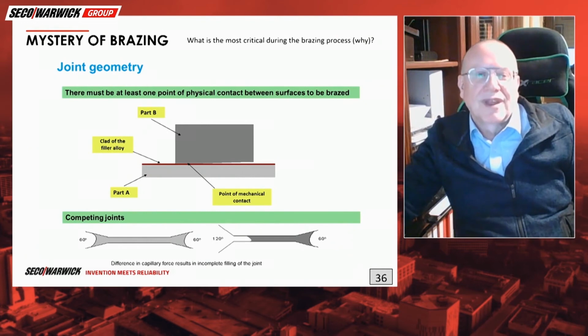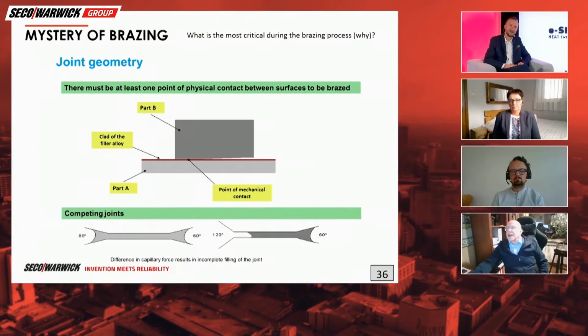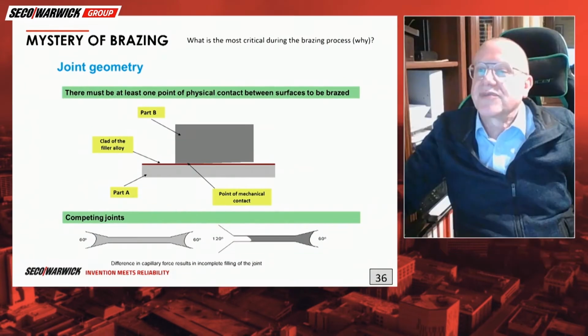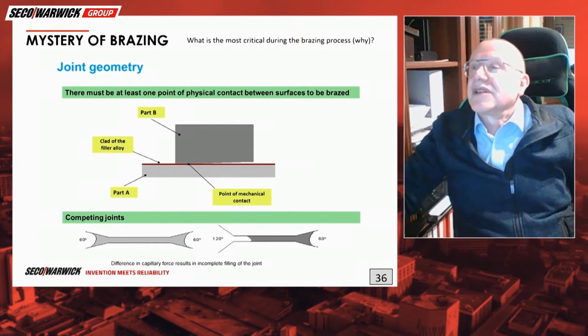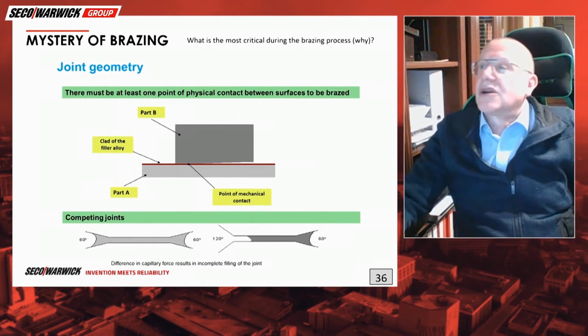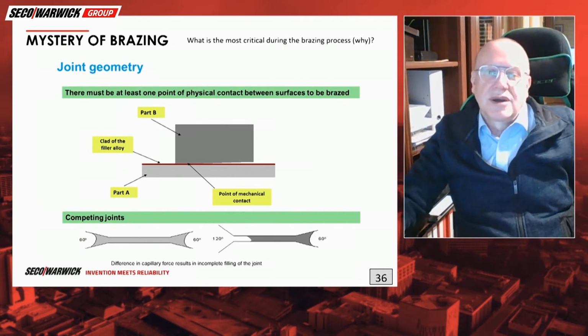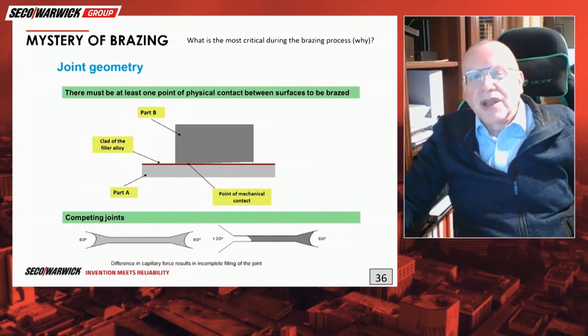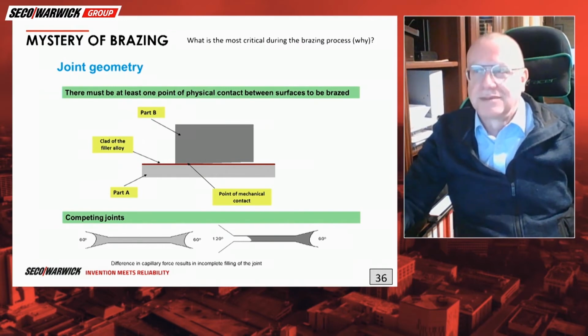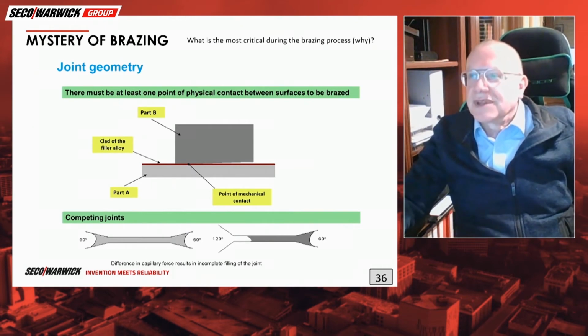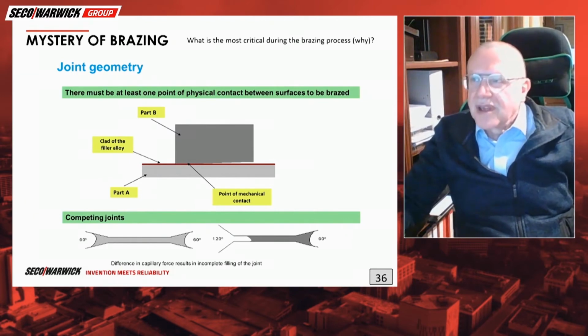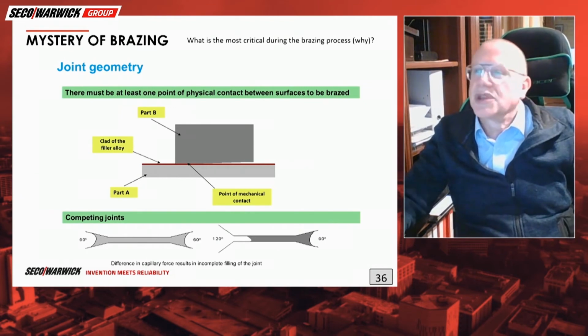Yes. And you mentioned something about joint geometry. I interrupted you, so please continue. The next parameter can be very complicated, but there is one general rule about joint geometry: there must be at least one point of physical contact between the surfaces to be brazed. Speaking colloquially, a filler alloy can flow on the surface, but it cannot jump. So somewhere a designer must make sure that at some point of the joint length, there is direct physical contact between the two brazed parts.